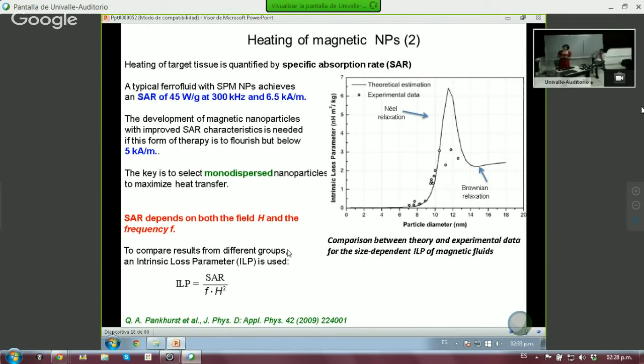So if we can go back to this heating, the second part of it, as I mentioned before, is that you have to remember the relaxation. Here what we show is the calculations, the theoretical estimation, and then the experimental data. As you can see, you go first through the Néel relaxation, and then as the particle diameter increases, you go through the Brownian relaxation.